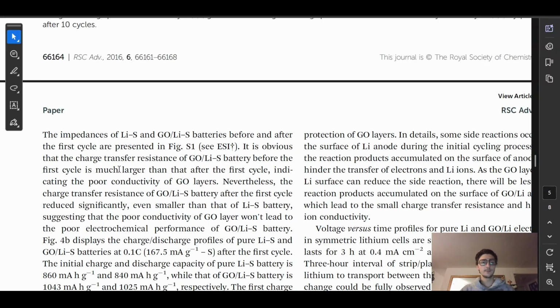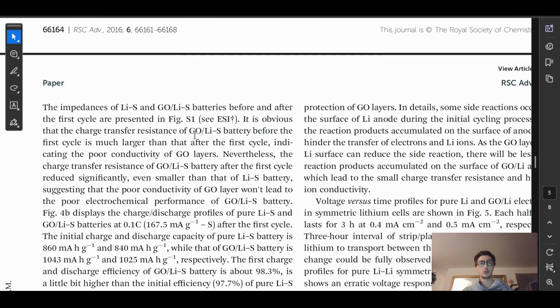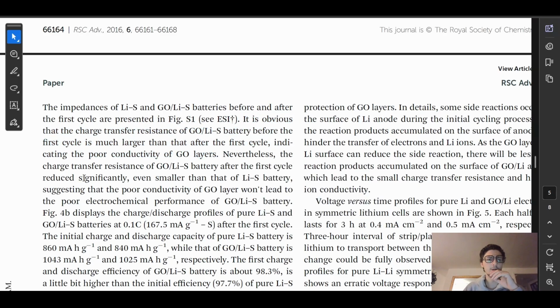It is obvious the charge transfer resistance of graphene oxide lithium sulfur battery before the first cycle is much larger than that after the first cycle, indicating the poor conductivity of graphene oxide layers. So when they say it is obvious like this, I'm just thinking, what are they talking about? I kind of want to see if I agree with them. It is obvious that the charge transfer resistance of the graphene oxide battery before the first cycle is much larger than that after the first cycle.